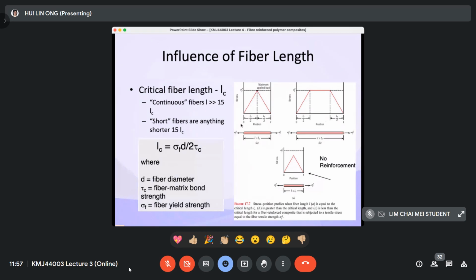So this is a long fiber. And then this one is just at the critical fiber length. Just at the critical fiber length is somehow quite dangerous. The fiber length is equal to the critical fiber length, so it's a little bit dangerous to use this kind of length to design a high strength and high stiffness polymer reinforced composite. So we usually advise to have more than 15. And this is short for sure, no reinforcement will happen, which is lower than the critical fiber length. It's not even up to the 15 times, but lower than Lc.